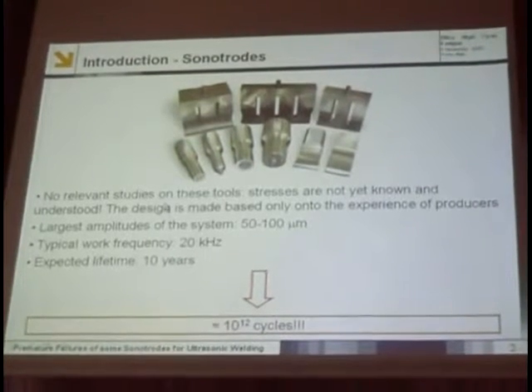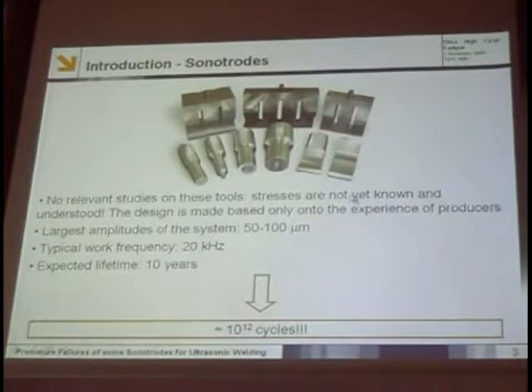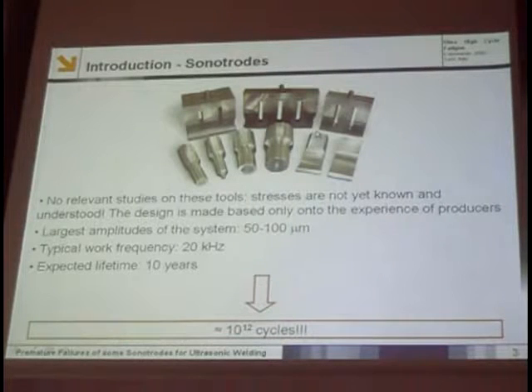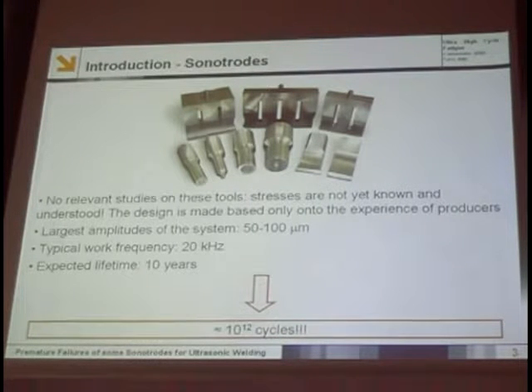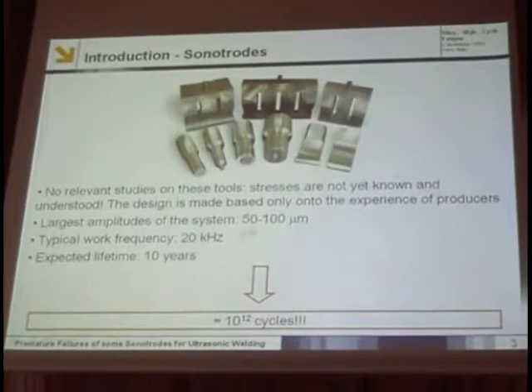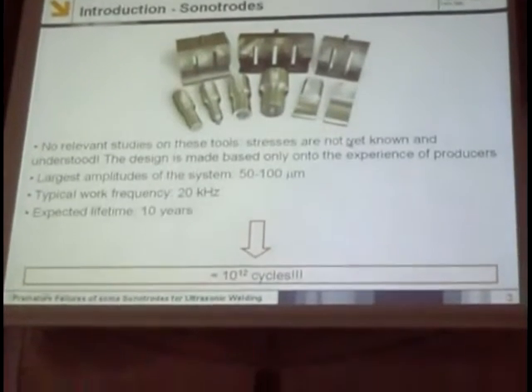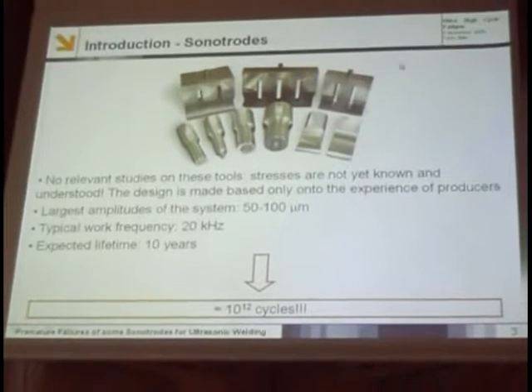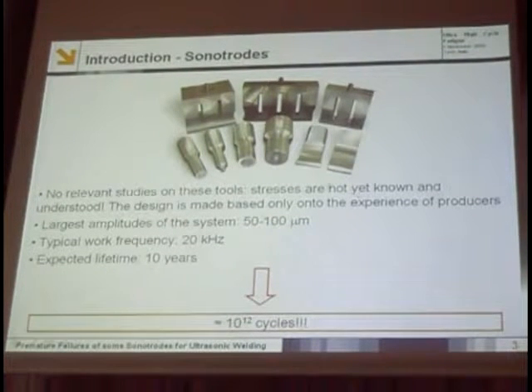And this is quite a brand new field, at least from the structural point of view, because in the literature there are very few papers on sonotrodes, and all the papers are focused only on the dynamical behavior of the sonotrode, but no one on the structural strength. As I saw, the largest amplitude of the working system is between 50 and 100 microns.